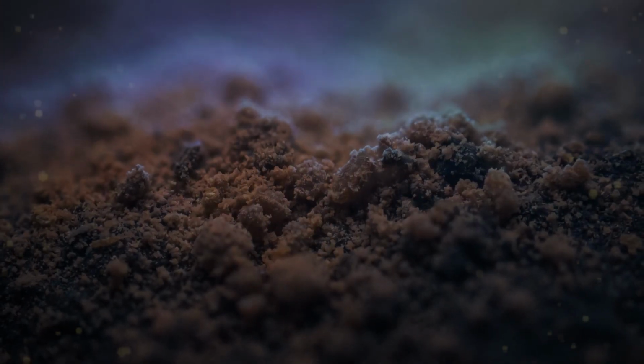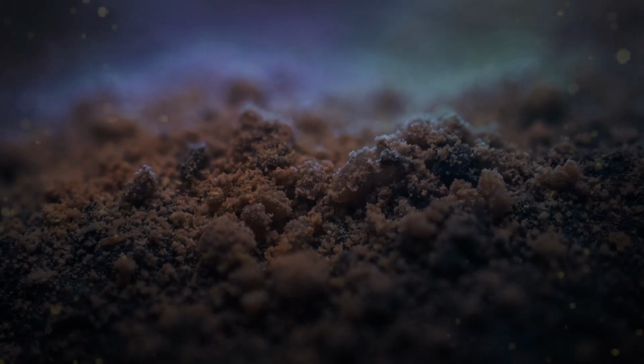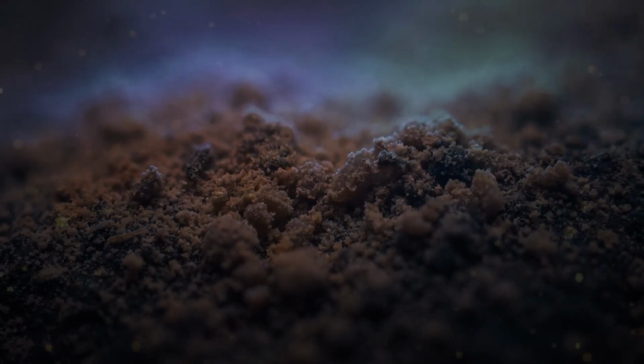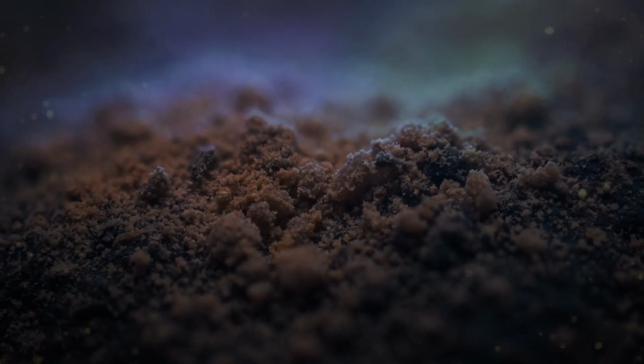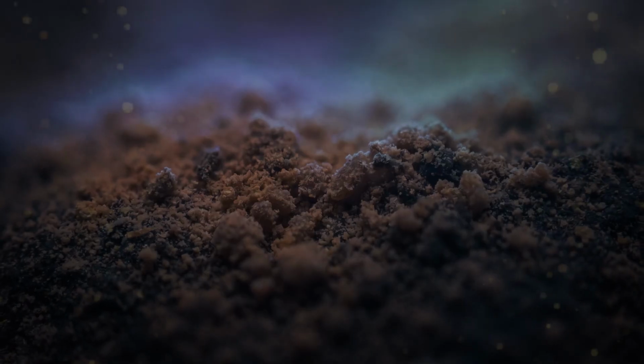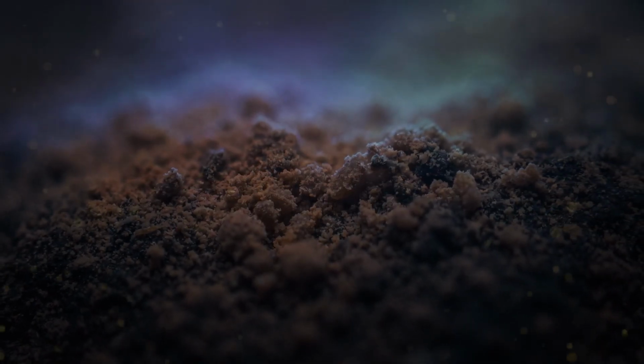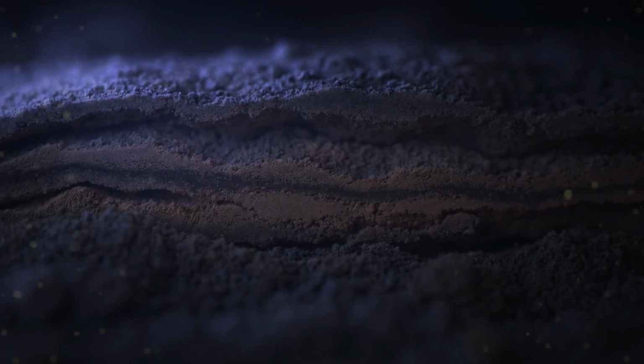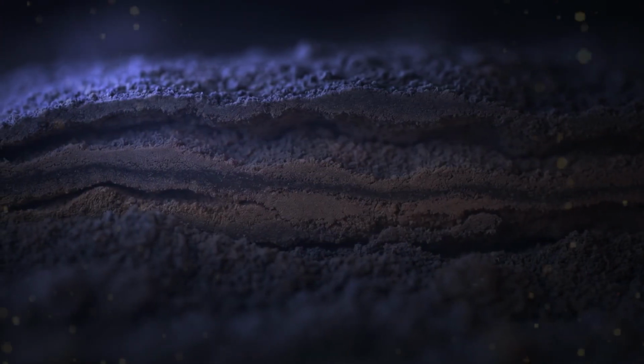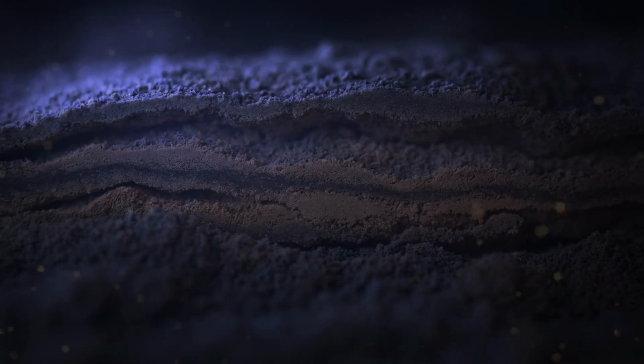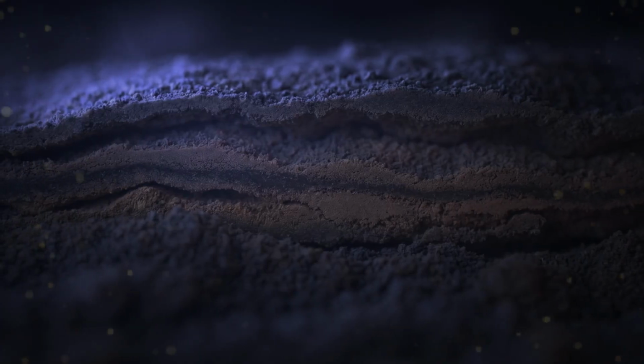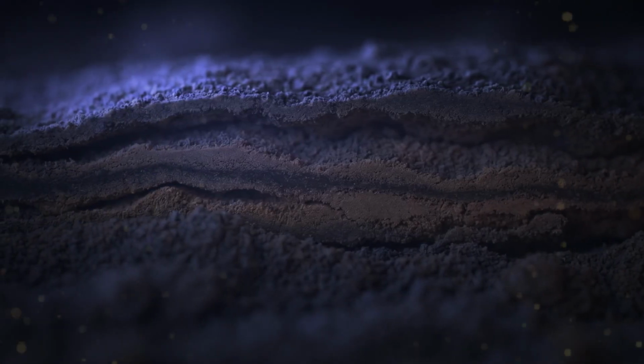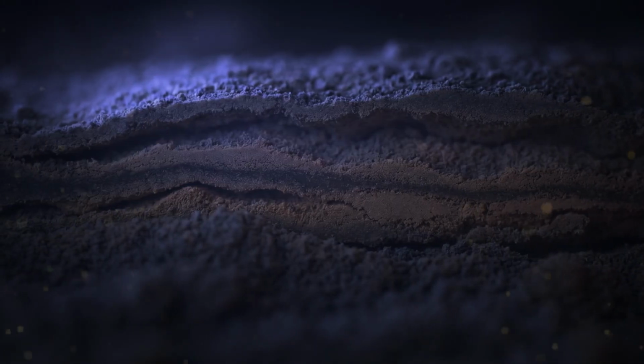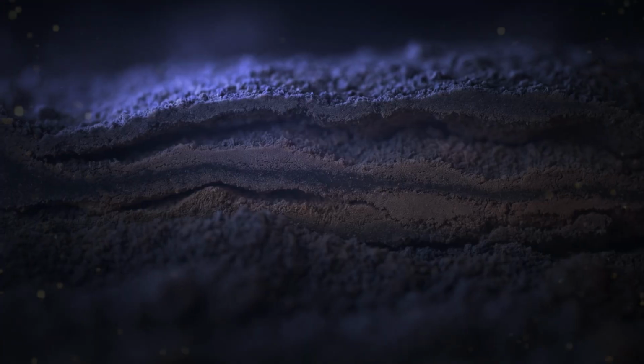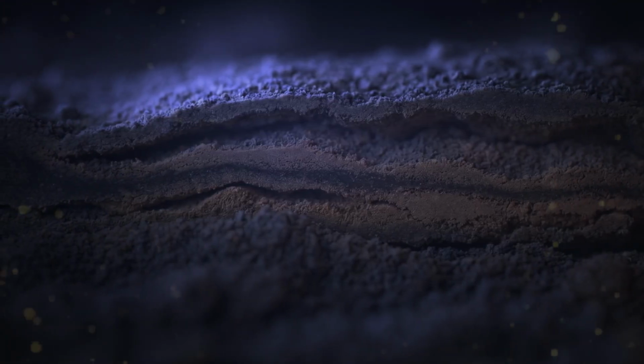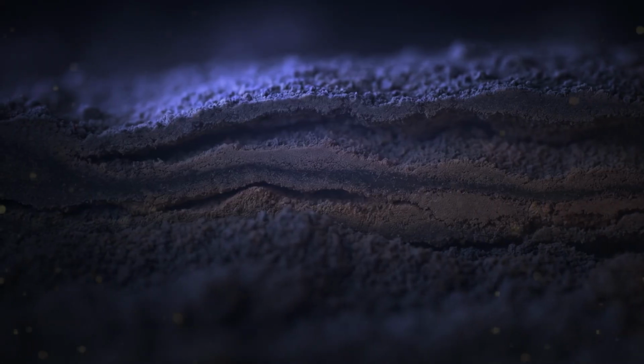Its presence in the Martian dust is significant precisely because ferrihydrite is not a stable end state. It should, under conditions allowing sufficient energy and time, transform into hematite or goethite. Where it persists on Mars, in the fine reddish dust that blankets the surface and fills the atmosphere, the interpretation is that it formed under conditions too cold or too brief for the more stable minerals to crystallize fully, and that those conditions then changed in a way that preserved the ferrihydrite rather than allowing it to transform.